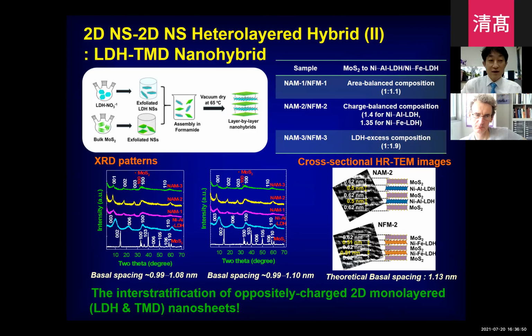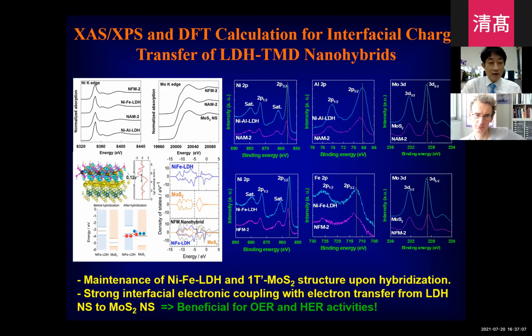We can synthesize the layer by layer ordered structure from the LDH and the molybdenum sulfide. We confirm the layer by layer ordered superlattice of the molybdenum sulfide and LDH from the XRD analysis and cross-sectional TEM analysis. We also examine the XANES spectra. So the hybrid material shows the typical nickel and iron XANES spectra of the LDH. Also, in case of Mo K-edge, it shows the typical 1T prime molybdenum sulfide structure. So from that, we can confirm the maintenance of the nickel iron LDH lattice and 1T prime molybdenum sulfide structure after hybridization.